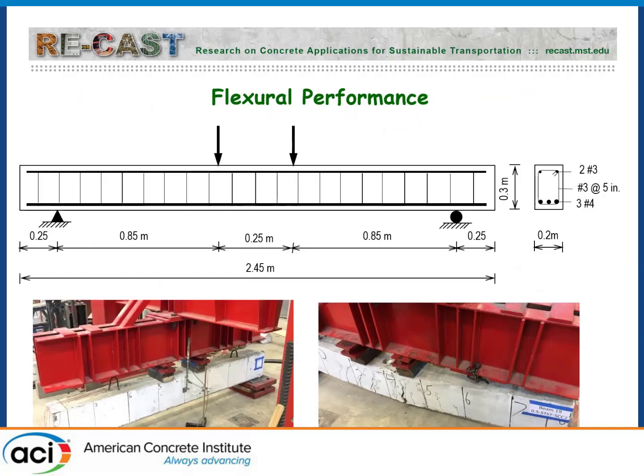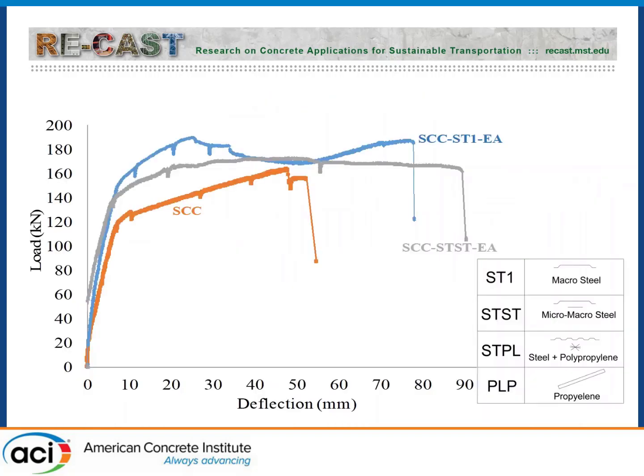All right, so we also did some limited flexural testing and shear testing. We also looked at how much steel we can reduce by adding fibers, but I'm not presenting this here. So, the same amount of steel, adding 0.5% of the two steel fibers. And you can see here the load deflection behavior. In orange, you have the SCC without fibers, and the 0.5% fibers, the two types of fibers. Again, we selected the one in gray, which is a combination of micro-macro.